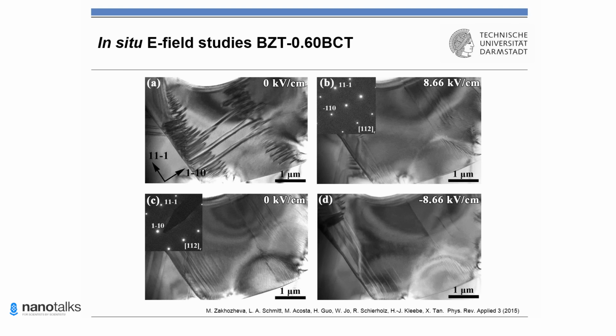Basically, this agrees with the high coercive fields measured when approaching a tetragonal symmetry. Therefore, higher fields are required to achieve a proper poling of BZT-xBCT, which is located very, very deep in the tetragonal region of the phase diagram.